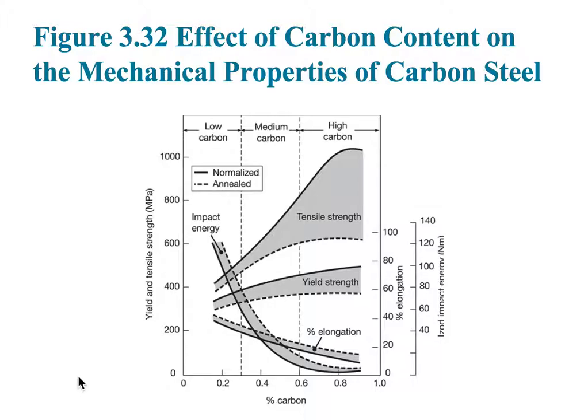The other thing is that the composition also makes a huge difference. Say for example, if you have a regular carbon steel and you are adding carbon to it, your yield strength might go up, your tensile strength might go up, but its impact energy goes down drastically. And if your impact energy goes down, you can also assume quite easily that its fatigue resistance also goes down. So increasing the strength is not always the ideal thing to do, especially for fatigue resistance.